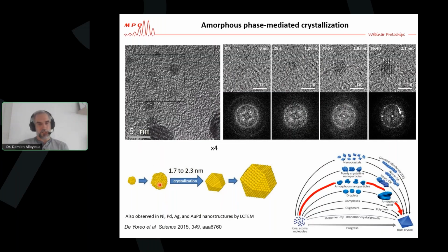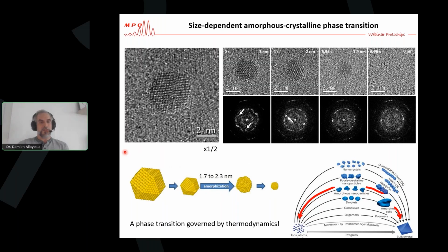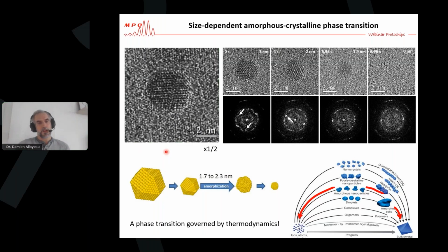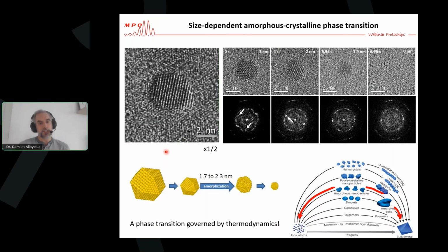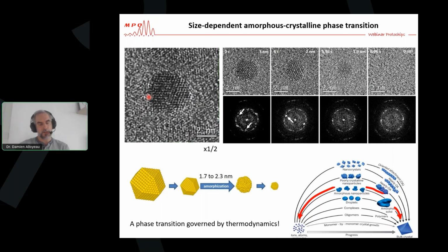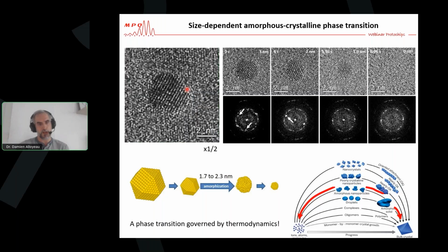So to answer this question, is it due to thermodynamics or is it due to kinetics? We wanted to know if we have the same phase transition during the etching. And that's what you see on this video. Here, you observe the isotropic etching of the gold nanoparticles in the liquid cell due to Ostwald ripening.